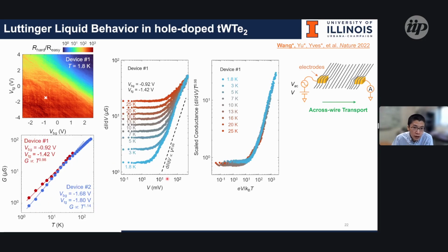We can also perform external bias dependence measurements. With external bias, you can see the differential conductance shows a power law at very high bias, mimicking the behavior people have observed in carbon nanotube systems. So it follows a power law in both cases.